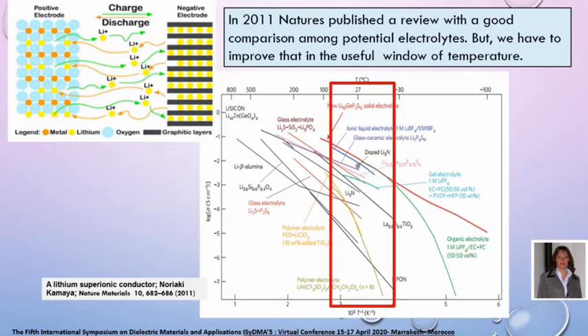Almost 10 years ago, we already had a long list of potential materials for electrolytes, but many of them don't have a good performance in the appropriate temperature range, between 60 to minus 20 Celsius degrees, because they have low conductivity or large activation energy. Or worse, they are too expensive and not green.